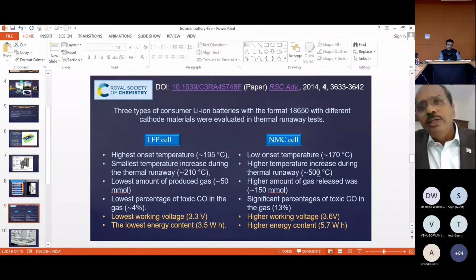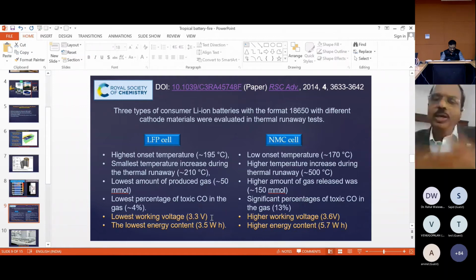That means your internal temperature is going up very fast. The lowest amount of produced gas is 50 millimole, while it is 150 millimole for NMC, and the lowest percent of toxic gas is 4%, while NMC has 13%. Of course, for NMC, the voltage is 3.6 volts against 3.3 for LFP, so your driving range will increase.